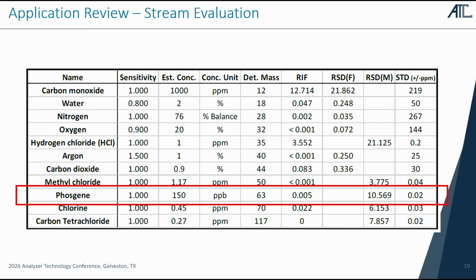The second part of that comes into the stream evaluation. Not only are we looking at what interferes, but then also how clearly we can see the signal from our target molecule versus the independent molecules around this. So this application gives us about a 50 ppb detection limit. We have very low interference from other chemicals, and we have a very low standard deviation for the system, but we would have about a 50 ppb detection limit.